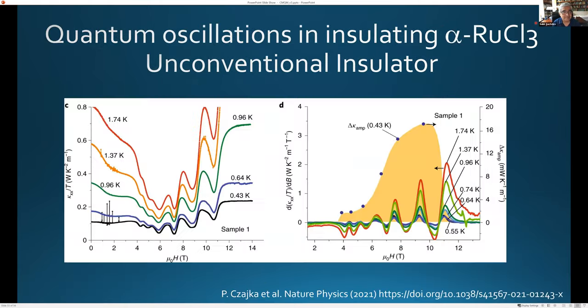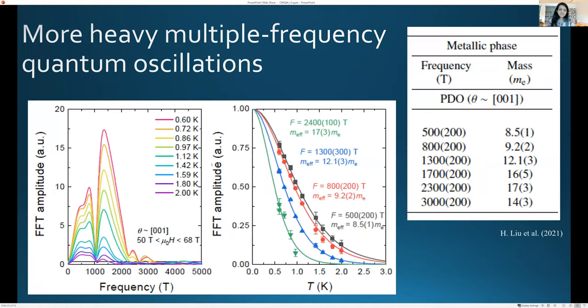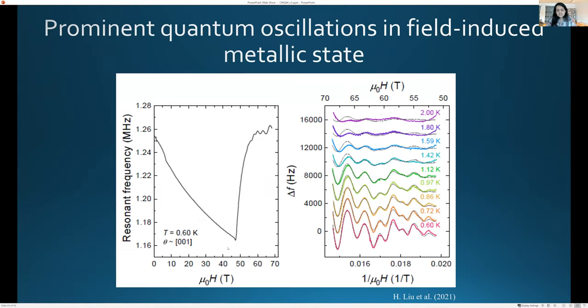Yeah. So I don't have the resistivity shown here. Sorry, this is sort of the inductance. But yes, at this field where you see a sudden change, if I were to show you the resistivity, it basically drops and becomes zero beyond this field. Okay, and do the quantum oscillations have a sudden change at that field? Yes, they become much bigger. But the same frequencies? You start seeing higher frequencies beyond that range. So two things happen when you go into the metallic phase.